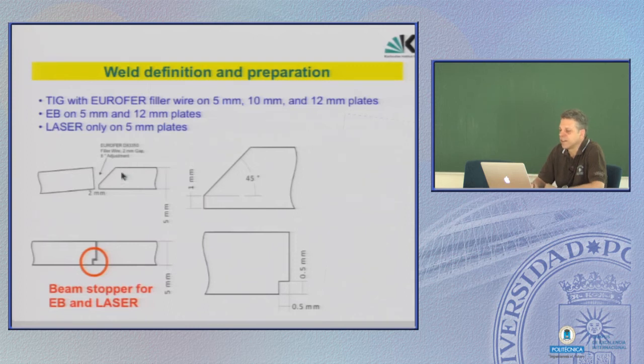This is in that case a 45-degree notch on the one side of the plate, and since there are internal cooling channels, you have to avoid that the weld is going outside the back end. There is also a small step at the final stage.